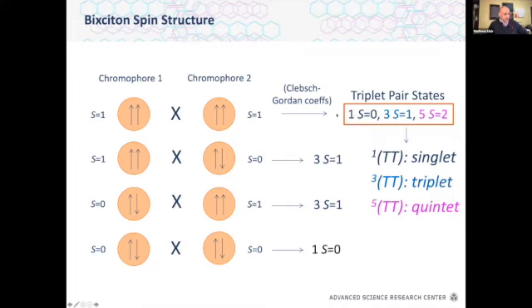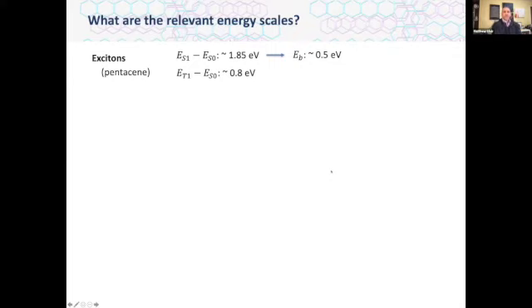So we get 3 possible net magnetizations, a singlet, 3 triplets, a set of quintets. Again, let's not worry about the counting number. And we're going to label those as our Biexciton states. And we're going to call them 1TT for the singlet, 3TT for the triplet, 5TT for the quintet, and so on and so forth. So let's look at the relevant energy scales for each of these, the singlet state, the triplet state, the Biexciton, and these sublevels. So the excitons themselves, I'll pick one particular singlet fission molecule, pentacene, just to be consistent. So it has a singlet exciton of something close to 2 volts, and a triplet energy slightly less than a volt. So it satisfies, again, our conservation of energy criteria.